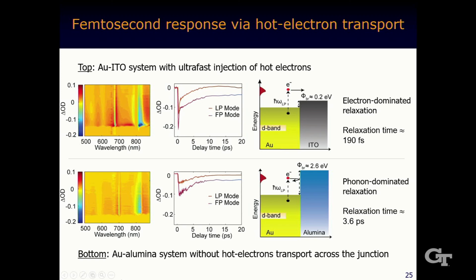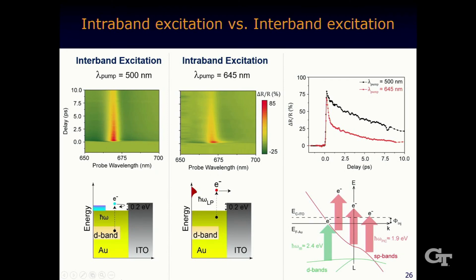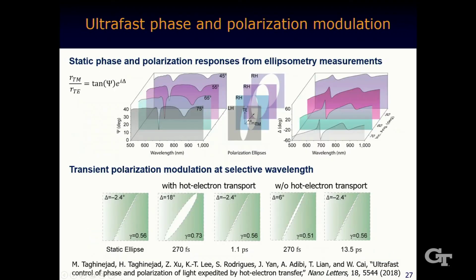In the control experiment where the ITO is replaced by alumina with a huge Schottky junction, so no electron can enter the alumina, you can see the modulation is much slower and also much weaker because you don't have this fast response at all. And let's skip this part because this page is related to the interband and the intraband transition of a metal, and it gives rise to different responses in terms of time domain and spectral domain.